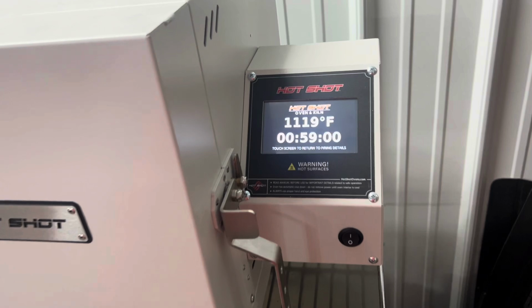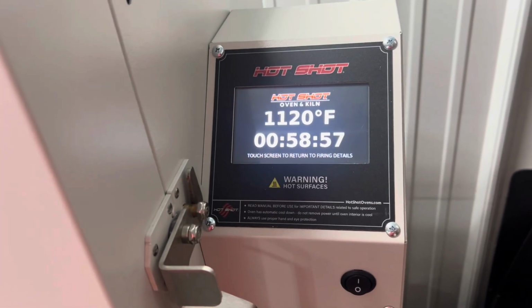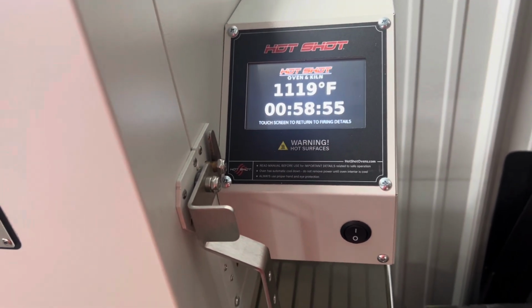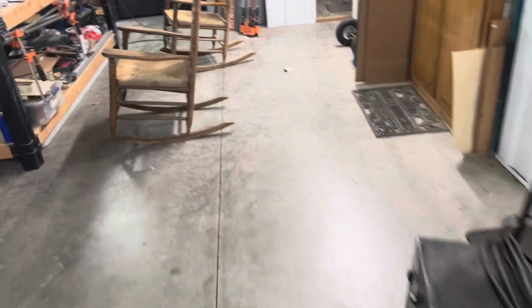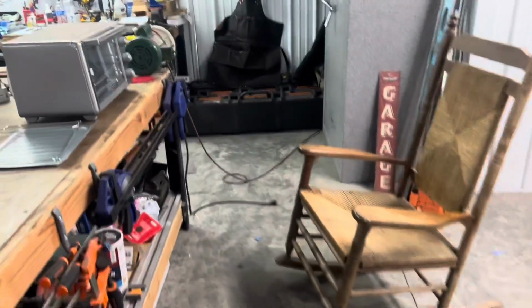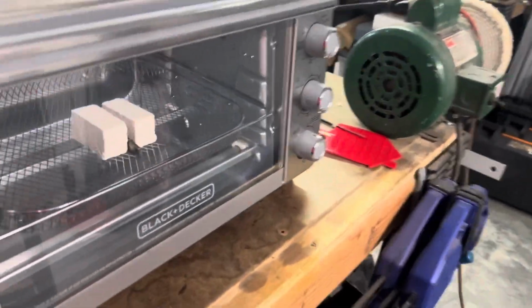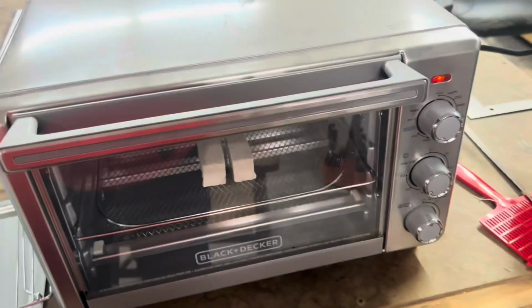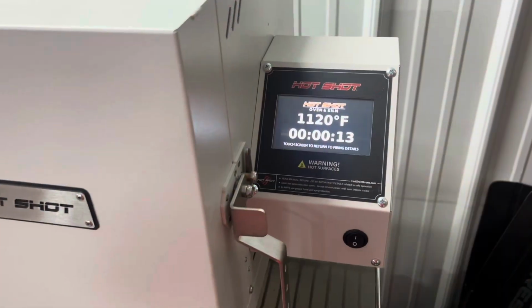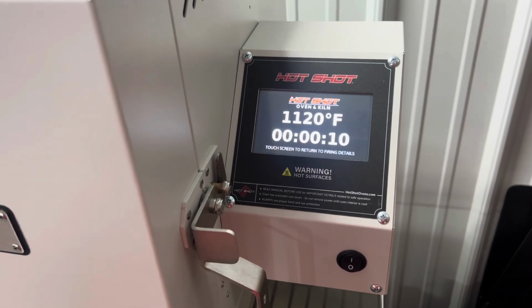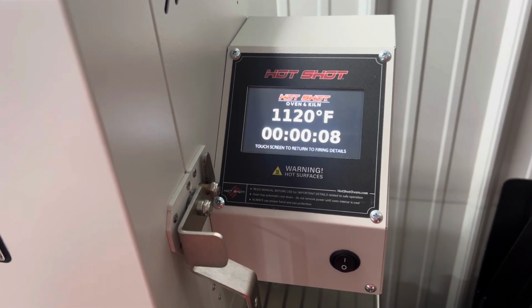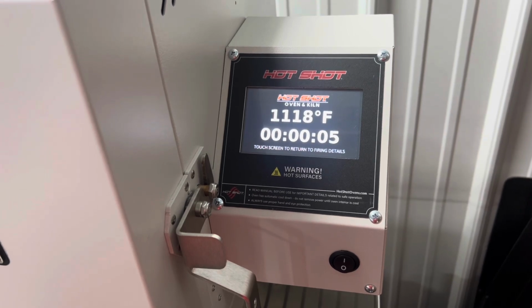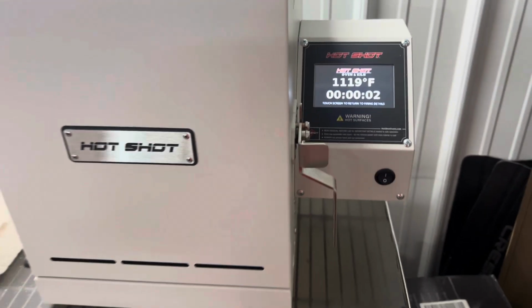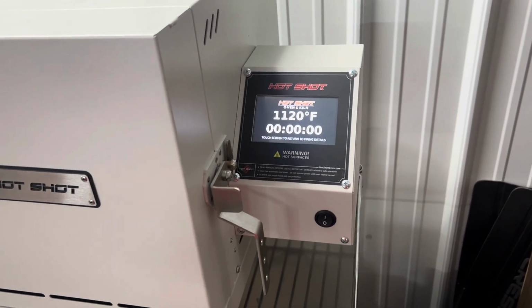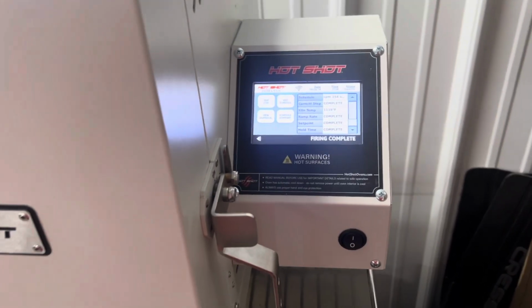Now we're on the temper cycle, 1120 degrees. We lack 58 minutes and 55 seconds on the spring. On the other side of the building, we've got our little toaster oven at 400 degrees, set on 2 hours to temper our blade. So that way we don't have to wait. And as you can see, we're counting down for the last 2-hour temper cycle at 1120 degrees Fahrenheit for the back spring, CPM 154. Counting down, and it is finished. Cycle complete.